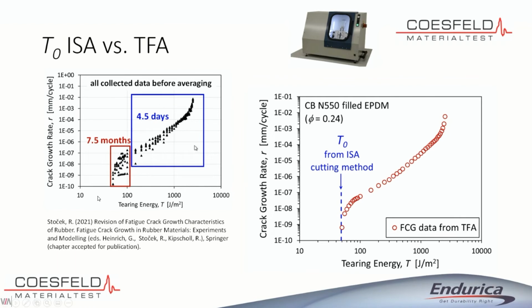So there's two sets of results here. On the left, you're looking at results that were measured on the Coesfeld Tear and Fatigue Analyzer. That's a dynamic system that can measure the fatigue crack growth rate curve. And in 5 days, you can reach down to a crack growth rate of about 10 to the minus 7. But in order to observe the fatigue limit, you have to keep going. And so we actually did run a test for about 8 months to get us down to a rate of about 10 to the minus 9.